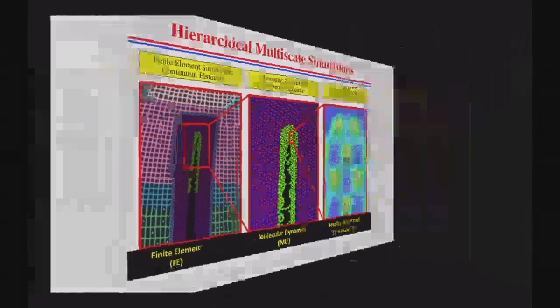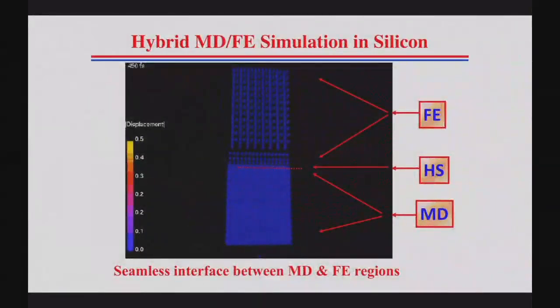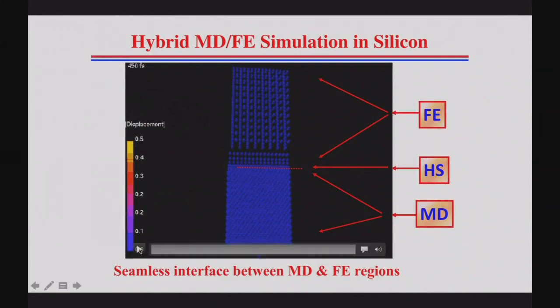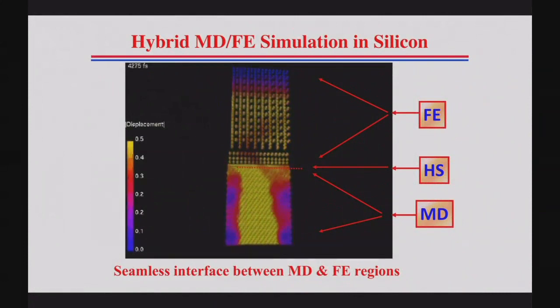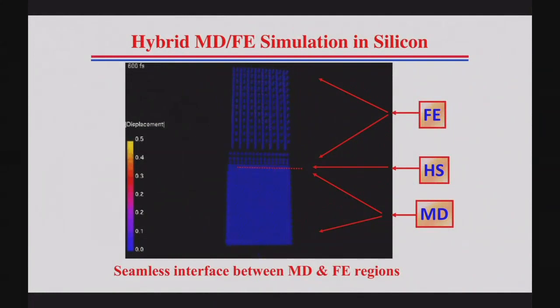For example, in this one, this is a hybrid MD and finite element simulation in silicon. The lower part is MD, the upper part is finite element, and the two are joined by something called the handshaking region, HS. We send a stress wave through the system, and as you will see, there are no reflections. It goes smoothly through the handshake region into the finite element, and the point here is that these schemes have been joined seamlessly.